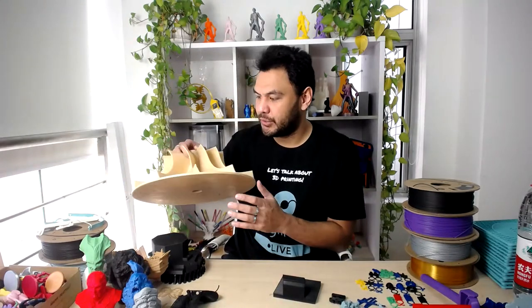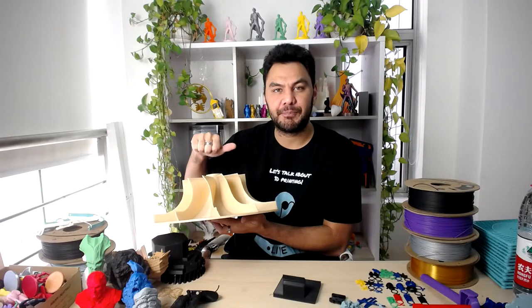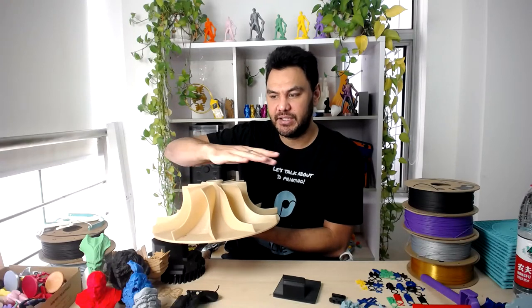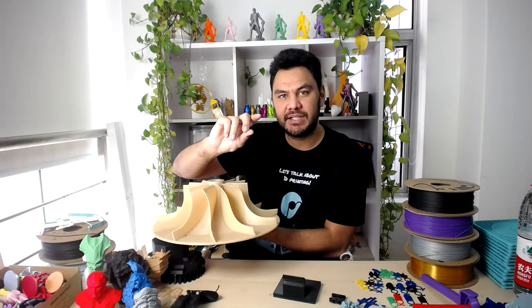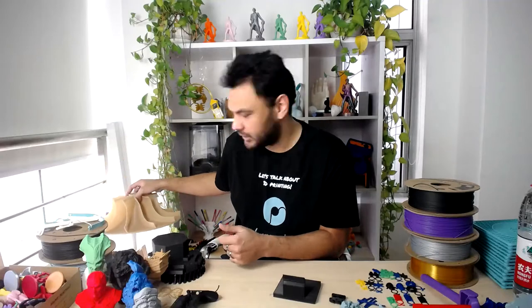When you anneal it, as its crystallinity increases, it becomes opaque. Yeah, definitely. It's like PEEK, right? When you anneal the material, it will turn a little bit darker because the crystals will reflect the light differently. I don't know if you've seen some video with PEEK, but it's the same. When they print PEEK, the bed is very hot, and then you will see it's darker towards the bed because it will crystallize on the bed slowly. So yes, you're totally right.